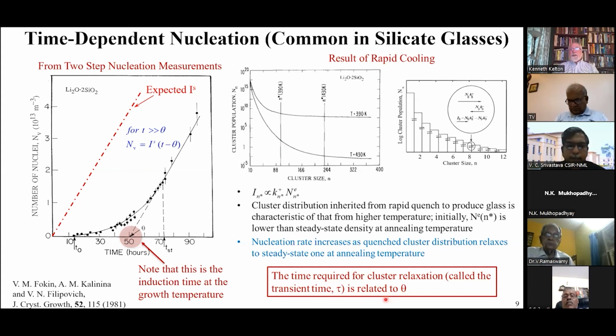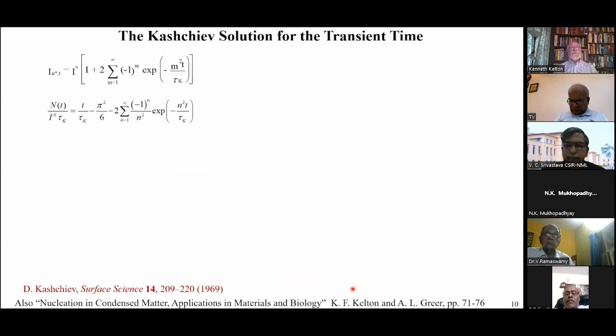This time, which I call the induction time, is related to this relaxation time of the distributions, which I'm going to call tau. Now, I don't want to go through the mathematics, but there is a solution for this, which is first given by Kashchiev And he showed that the nucleation rate as a function of time is given by the steady state rate multiplied by this sum. And in particular, he showed that if you look at the number of nuclei produced and you normalize it to the steady state rate and this transient time, which is that relaxation time, which I've labeled tau k, then you get an expression like this.